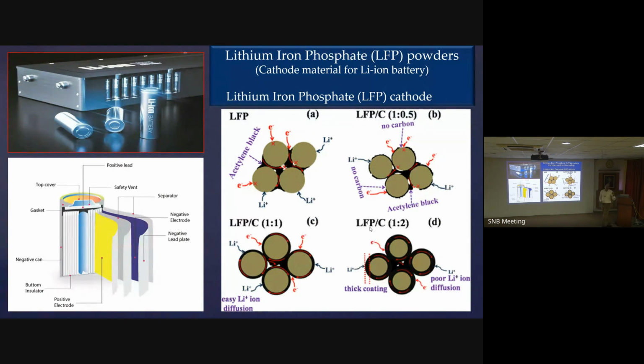It also has to be very small in size, because when you charge this cell for high power, it should be in nanoparticles. You cannot change the diffusion coefficient, but you can change the diffusion length by reducing size. So now I want, at large scale, nanoparticles coated with the bare minimum carbon, but it should have the conductivity to collect the current and give it to the current collector. So this is the process we optimized.